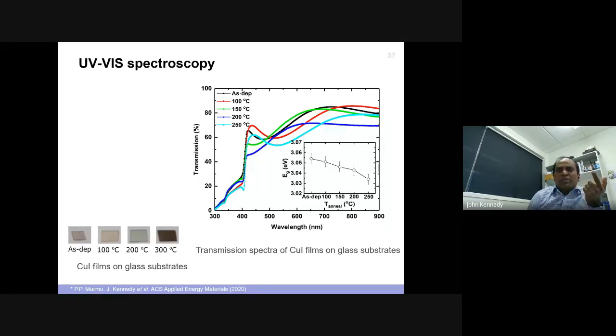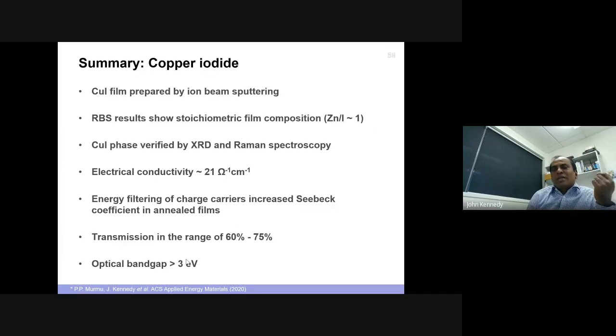You can see in the picture here, on a glass substrate, you can still see through the glass, but there is actually a 2 nanometer copper iodide film on it. So that shows you visibly it's transparent. And this is again a beautiful result, because if we can optimize and improve the transmission, you can take the waste-free energy from the sun, going through UV, through your glass window, and harvest it. So this is the area we are currently concentrating on to optimize. Can we really get a high efficiency factor?